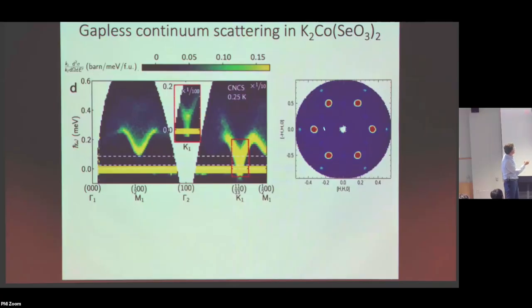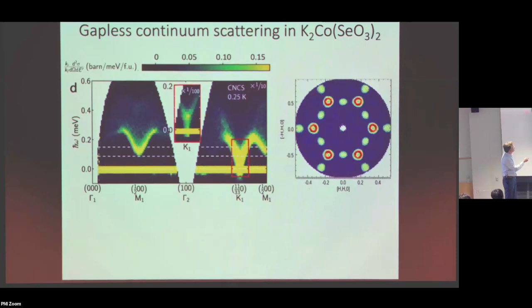Then you see these points which actually come from the M point, which I consider like a competing instability. You can see this is coming into view. If you look very carefully, then here at half of the K point, there's also a soft, lower energy mode there. That's not into view yet because I only showed the really low energy part. If I come up a little bit more, then you can see these six spots appearing here that come from this part here. These have now become stronger because I'm passing through this minimum here.